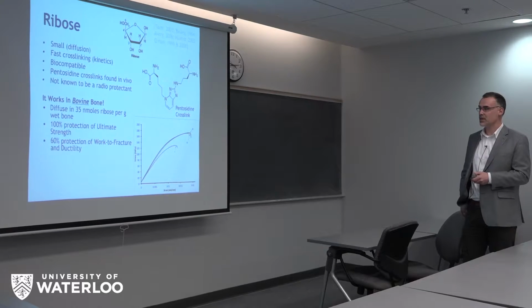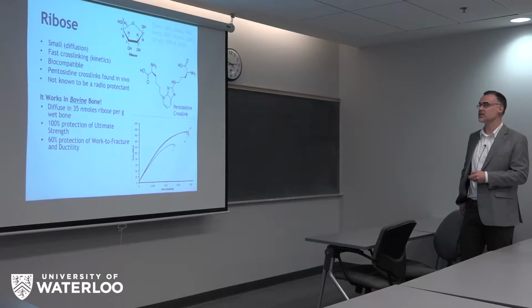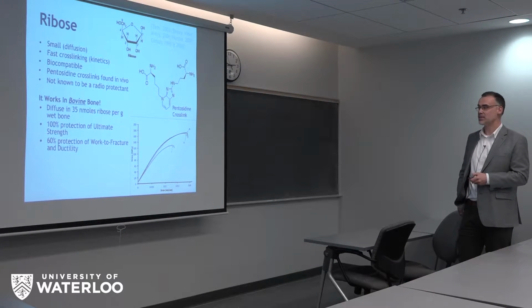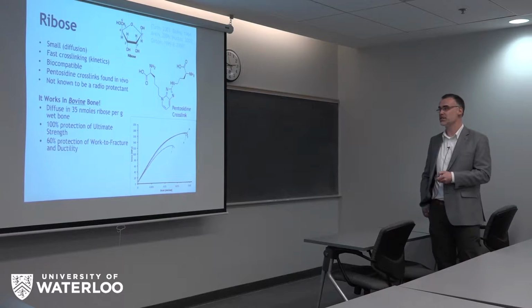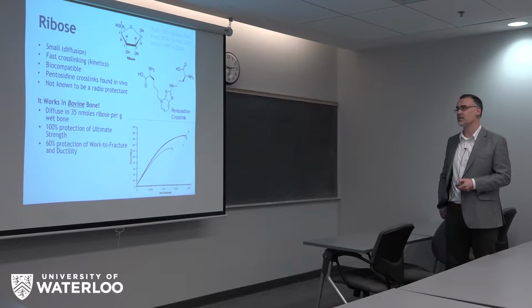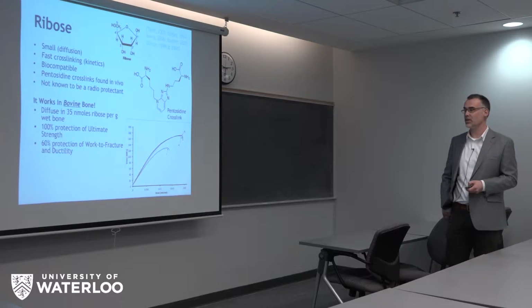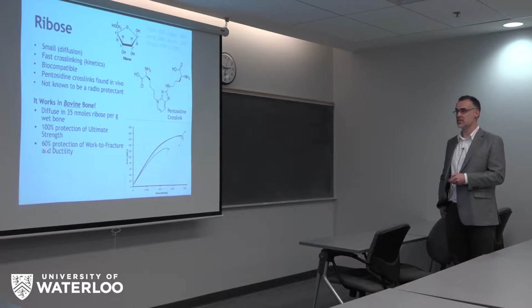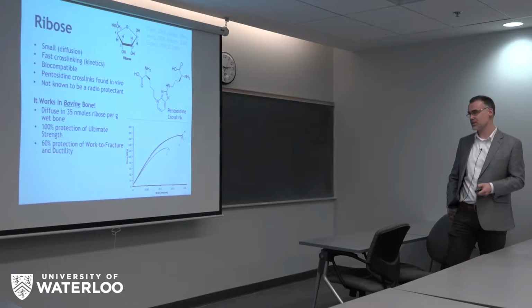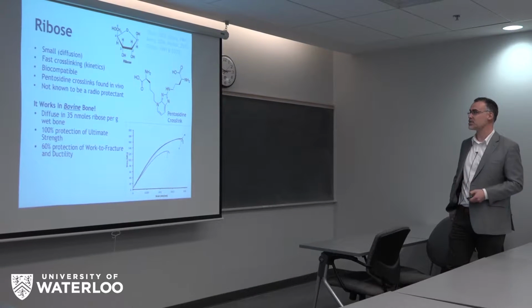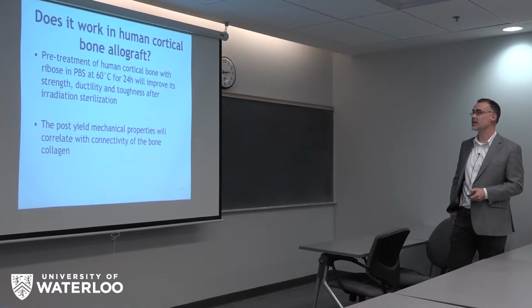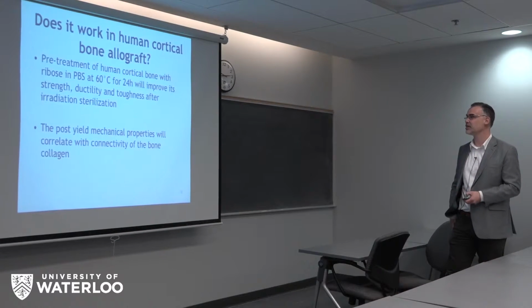We used radio-labeled ribose to measure how much ribose was actually being incorporated into the bone matrix, and then measured 100% protection of ultimate strength and 60% protection of work to fracture and ductility. And these are some representative curves here from 3-point bending. Oh, and you can read about that here.